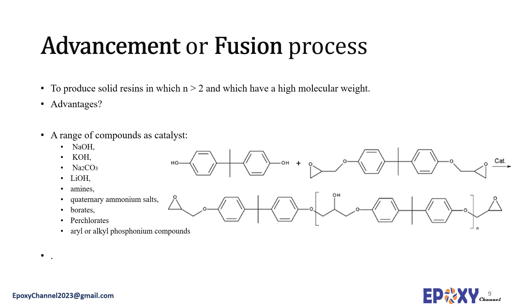The advancement process is a two-step process using the reaction of bisphenol A and epichlorohydrin under a catalyst such as a quaternary ammonium salt. The first step uses an addition reaction to form a diphenyl propane chlorohydrin ether intermediate, and the second step is carried out in the presence of NaOH to produce the epoxy resin via a ring-closure reaction. The advantages of the two-step process include short reaction time, stable operation, small temperature fluctuation, easy process control, short alkali addition time, avoidance of large-scale hydrolysis of epichlorohydrin, and good stable product quality with high yield. The domestic E51 and E54 epoxy resins are synthesized by this two-step process.